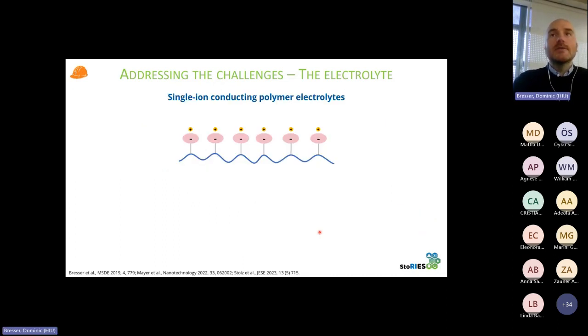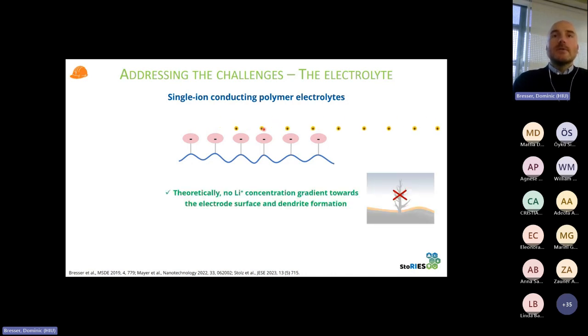One potential alternative that we and others are working on are so-called single-ion conducting polymer electrolytes. The idea here is that we do not have to add a salt, like lithium TFSI, LiPF6, or any other, but the polymer as such contains the lithium cation. So we covalently tether the anionic group to the polymer backbone as depicted here, and then we have the lithium cation. In fact, the only charged species that eventually is mobile in such systems is the lithium cation. And so this theoretically provides the great benefit that we don't have any lithium concentration gradient being built up, different from the PEO with the lithium salt, where the anions move to the positively charged electrode and the cations move to the negatively charged electrode, preferably.